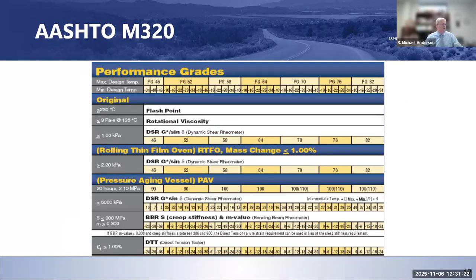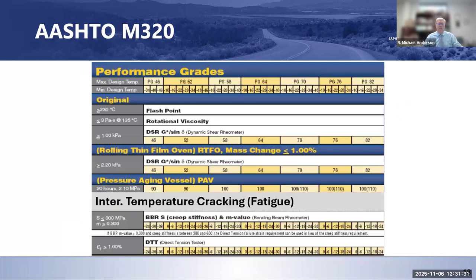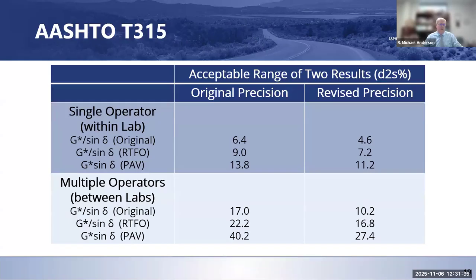So ultimately, this is what led us to AASHTO M320. The intermediate temperature parameter here is the DSR G star times sine delta after PAV aging. That's our intermediate temperature for cracking fatigue. Some of the challenges we had early on were high variability in the DSR, particularly at that intermediate temperature. This was what was reported originally in some of the first proficiency sample programs from AASHTO Resource, where between-lab variability for G star times sine delta was 40%, which is quite high. To put that in perspective, you could have a lab with a 3,400 kilopascal value and another lab with a 5,100 kilopascal value, and those would be considered within acceptable tolerance, statistically the same.